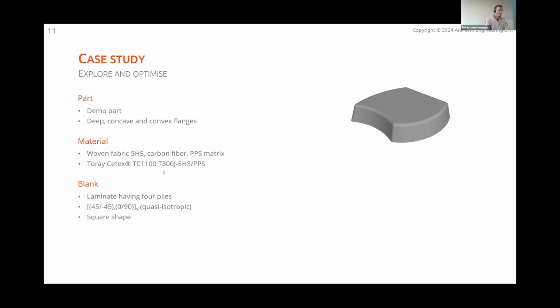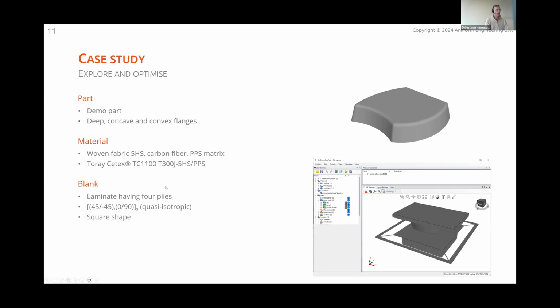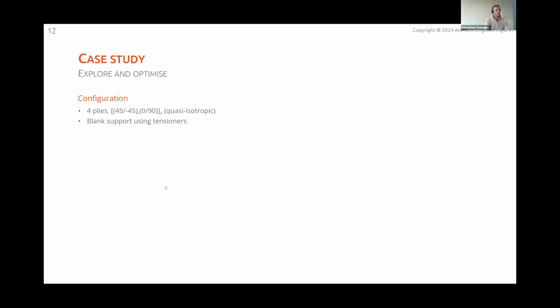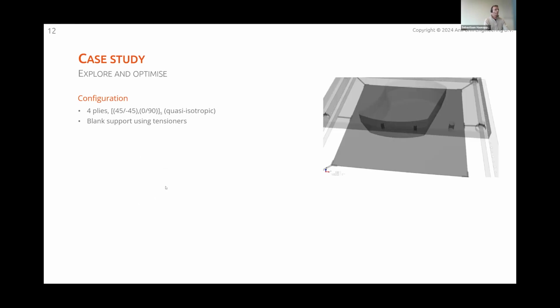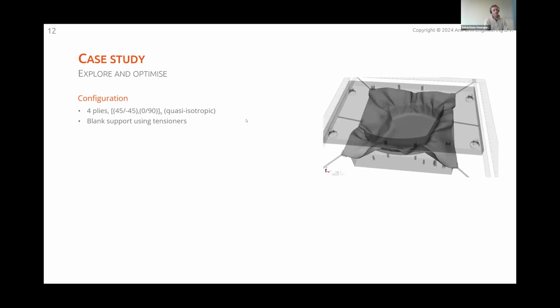We consider a blank. It's a laminate having 4 plies, initially stacked in a quasi-isotropic manner, so 45s on the outside, and in the center we have a 0/90 ply or 2 0/90 plies, and we consider a square shape of the blank. And you can model that then in AniForm pre-post and do a prediction. So about this simulation result with a quasi-isotropic layup, we have the blank, by the way, supported using tensioners, and then you typically get the result like you see here in the video.